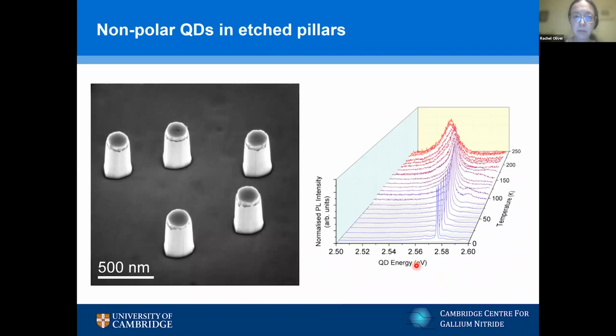Now, the simplest devices we make with these dots are still going to be optically pumped devices. I'll come on to electrical pumping later. And we just etch little pillars to help isolate individual dots and also to guide the light and improve light extraction. These were done in a really simple fabrication route. We disperse 200 nanometer silica spheres in a very sparse array across the surface and use them as a mask to then etch the pillars. So it's a microsphere or nanosphere lithography technique.